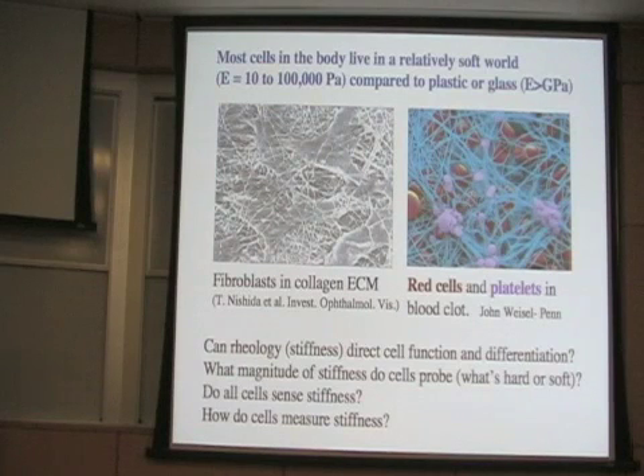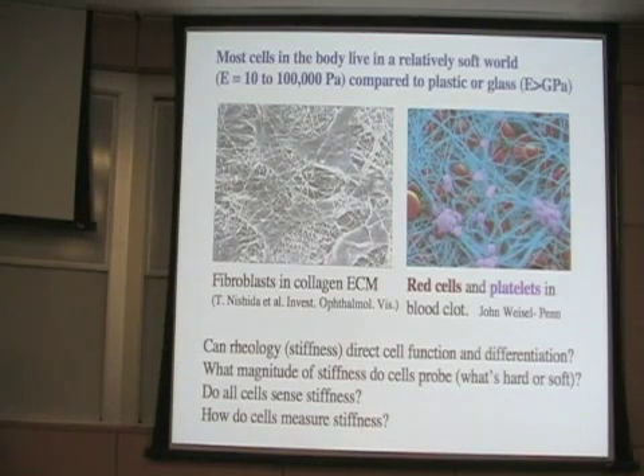And so the ability of these cells to stiffen the network is not because they're adding mass to the polymer matrix. It's simply because they're applying internal stress. And that internal stress ability to stiffen the network relies on the fact that these networks are intrinsically nonlinear elastic materials. They stiffen the more you strain them. And that's a feature that is not present in most synthetic elastomers, including the soft materials that most of us grow cells on. Okay, so those are the two kind of images I want to think about, and we'll look at these again later.